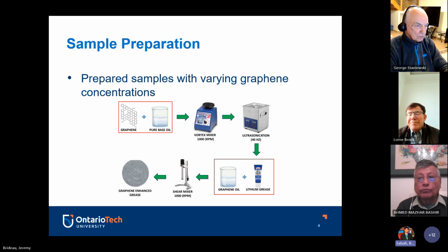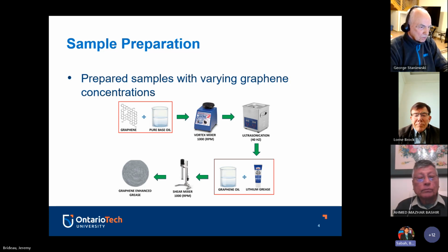Once we have the graphene in the pure base oil, we put it into a vortex mixer and mix it for around 5 to 10 minutes to make sure all the graphene is completely mixed in. Then we put it into an ultrasonicator. This ultrasonicator sends ultrasonic waves to break up all the particle agglomeration that could have happened during the mixing process. Then once that's finished, we put the grease into that mixed solution, and we shear mix it for 10 minutes until we have one solution.